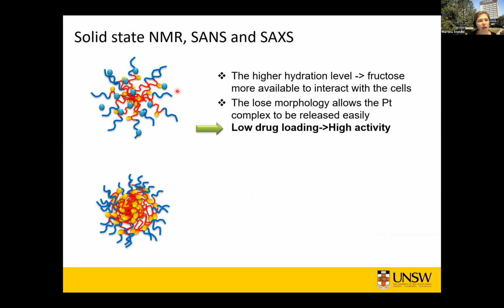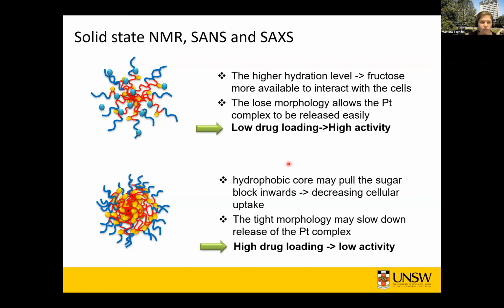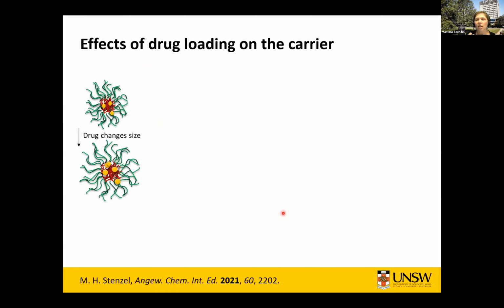So what we learned from this case is that if we have only a little bit of drugs in the core, we have very high hydration levels of the whole nanoparticle. So it's swollen with water. And because it's swollen with water, it can interact much better specifically with the cells. We have a quite loose morphology, and it also allows for the drug to be released. However, if we have a lot of drugs here, the nanoparticle is very tightly packed, and the drug release is very much delayed. And also because it's very tightly packed, it's very dehydrated. So these chains on the outside can't really interact with our cells.